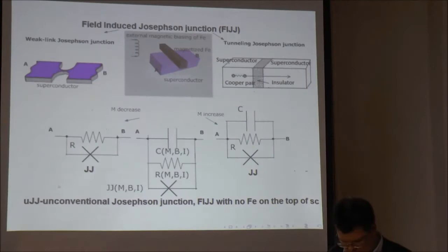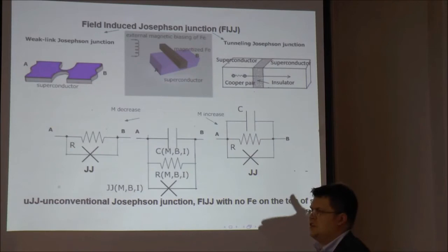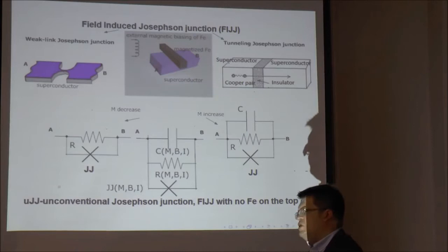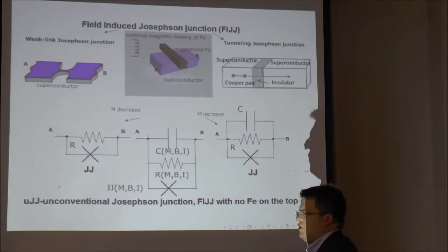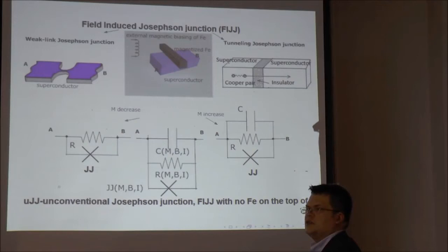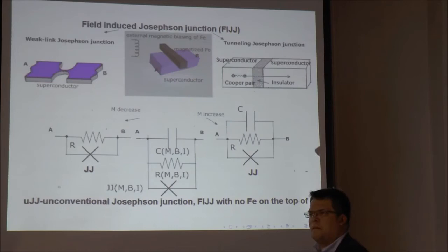If you have an interface, for example, superconductor and normal state, two metals, one is superconducting, one is not, for example, I don't know, Pb and copper, in close proximity to the superconductor there will be decay of concentration of Cooper pairs if you go deeper into the non-superconducting material, but still these correlations will survive if you are close to the superconductor. So there must be a certain length. Yes, there is the so-called superconducting coherence length. After that distance, the Cooper pair disintegrates.